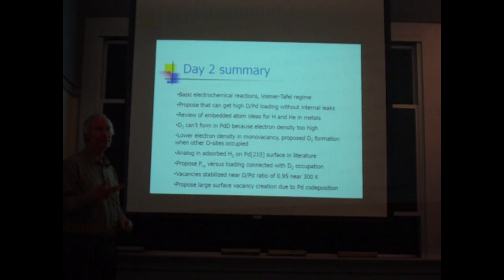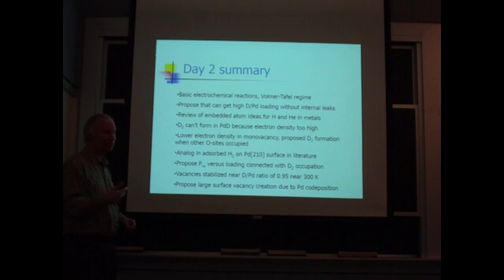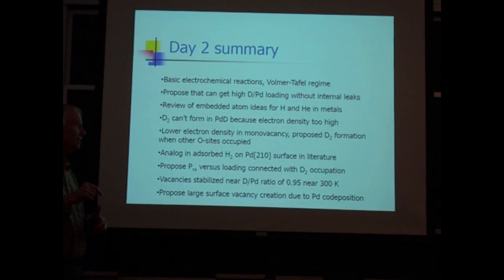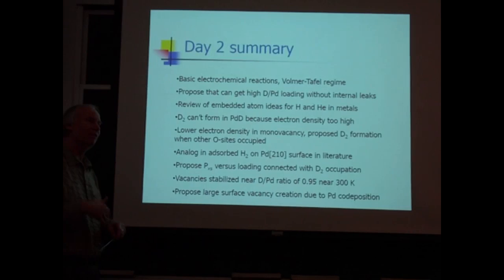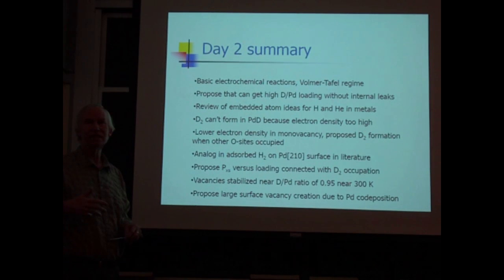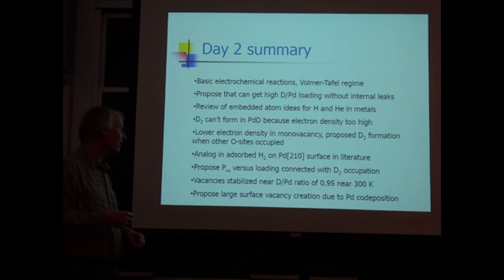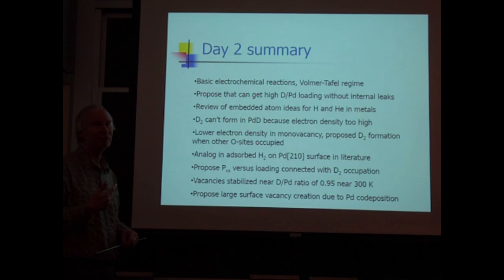So the idea is that in the Fleischmann-Pons experiment, in the lithium deuteroxide electrochemical version of the experiment, excess heat isn't seen at low loading, but above about 0.84 loading, excess heat is observed. So the proposal is that if we're making D2 in vacancies, well, D2 is unstable at low loading, because if the other octahedral sites around one vacancy are not occupied, then the D2 is happy to fall apart and occupy the unoccupied octahedral sites. So if you do some physical chemistry and calculate the D2 occupation as a function of loading,